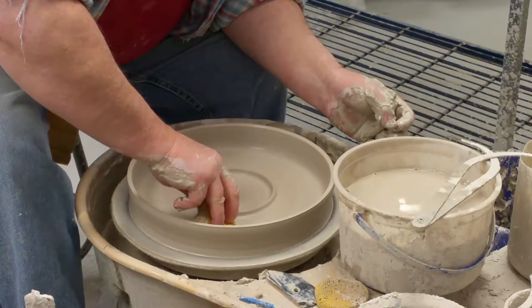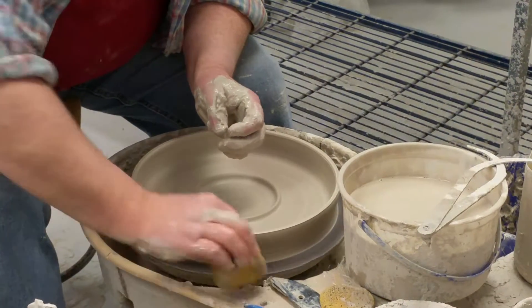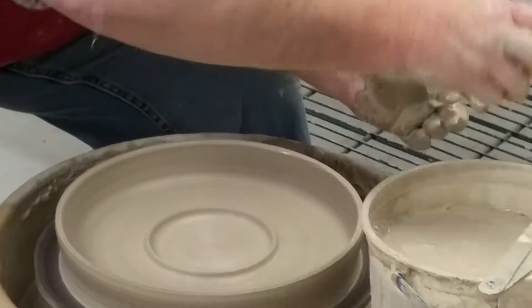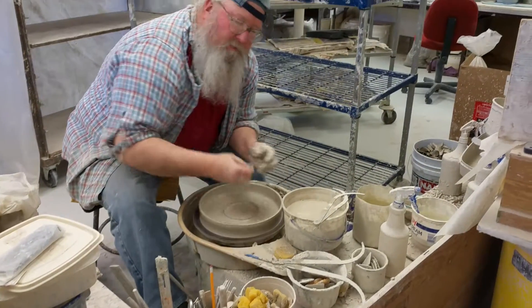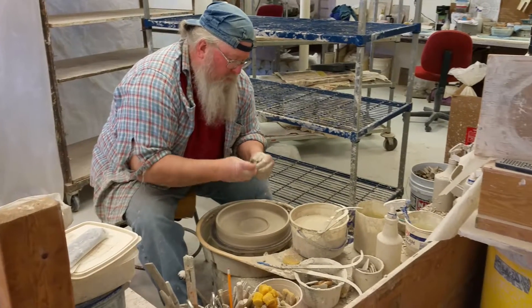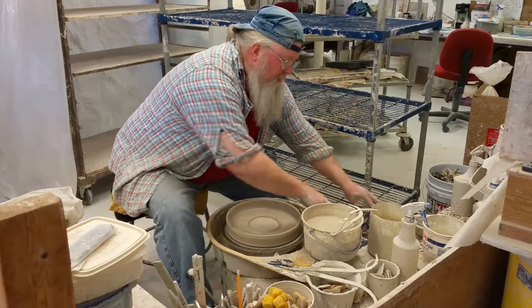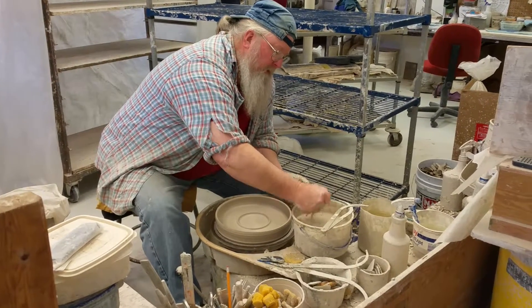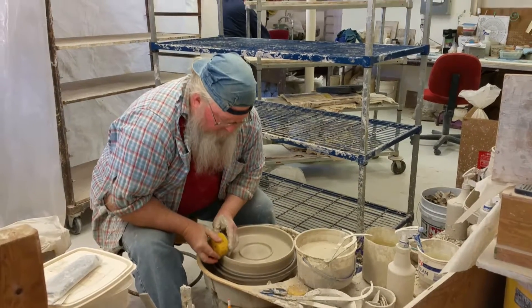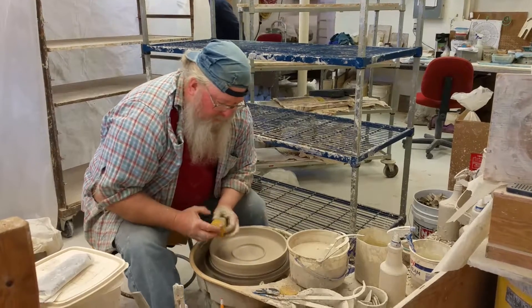That first firing goes up to 1,650 degrees Fahrenheit. Then for the second firing, once we take it out and put glaze on it, we put it back in the kiln and fire it to 2,250 degrees. In that second firing, the clay becomes what we call vitreous, which means glass-like, meaning it'll hold water even without the glaze. That's very much unlike low-fired ceramics, which need glaze to hold water and are still much more fragile. Stoneware — that's what we make — is much more durable and hard, less prone to chipping, and when finished it's dishwasher and microwave safe.